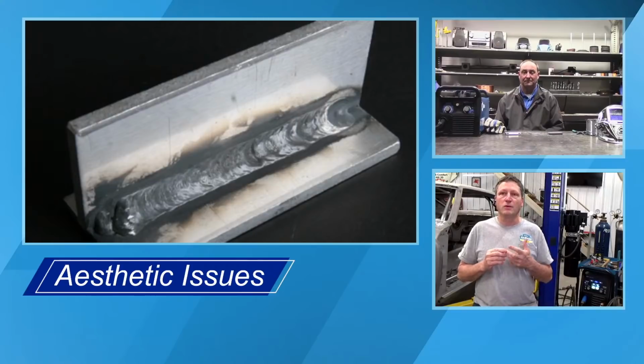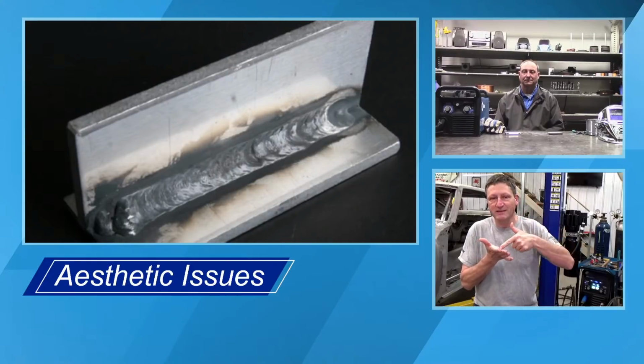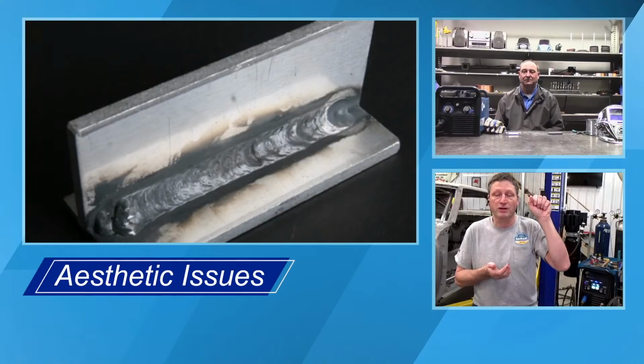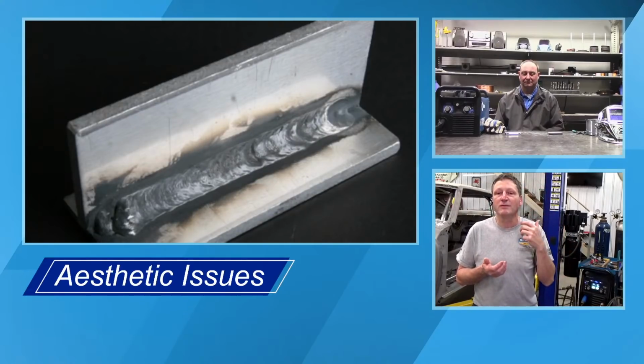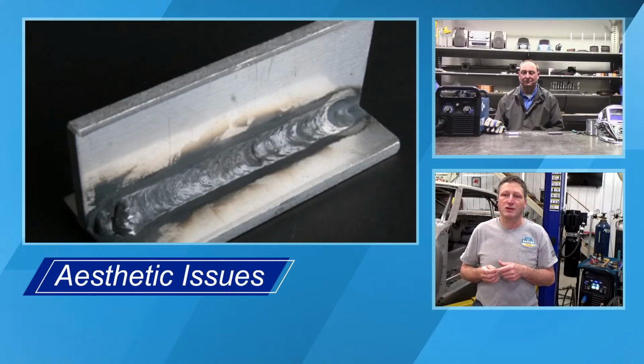So when you push the trigger and the wire comes down and hits the workpiece, the machine doesn't know you're welding aluminum and it just reaches a bunch of amperage to start burning off that wire. With aluminum wire, it could be too much amperage and pop, there goes the tip. So, again, pull a little bit longer arc length. Your contact to work distance would probably be the first thing. Another thing is obviously making sure you have the proper contact tips.